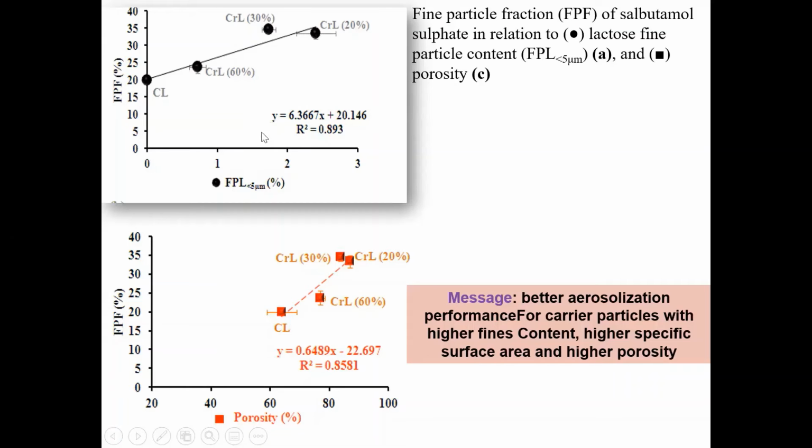But the important thing we're trying to tell is the prediction of fine particle fraction based on porosity. And you can see that simply, the higher the porosity, the better the fine particle fraction. So if you calculate the porosity of such formulations or such carrier particles, you can predict what's going to happen for fine particle fractions.